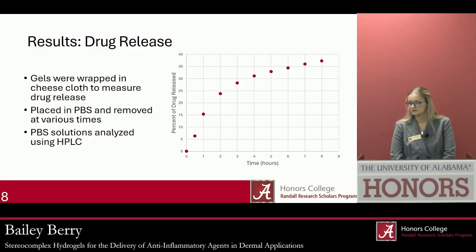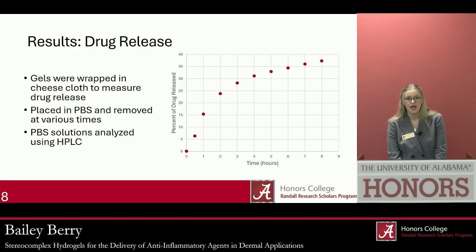You used D-lactide throughout this whole process, but did you do any trials using L-lactide? Yes, that's a really good question. We did do some trials with L-lactide, and we found that as compared to using D-lactide in the same ratios, D-lactide actually made a more stable gel than L-lactide, which suggests that these stereocomplexes are being created and are creating a more stable gel. But the L-lactide still forming gel suggests that the compound has gel-creating properties that are beyond its stereospecificity, but we do still see that the D-lactide gels were stronger, which suggests that the stereocomplexes are being made, it is trapped in the naringenin, and it is making the mechanical properties of the gel stronger.